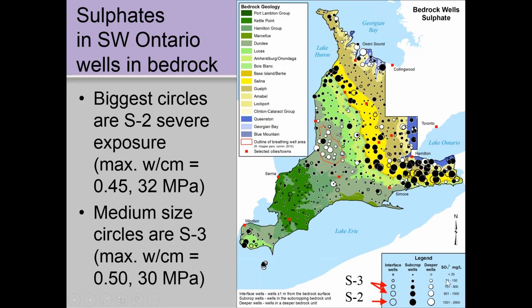Anything less than 150 is considered not a sulfate, so any of the smaller dots are not a problem, but when you get the bigger dots, that's where there are sulfates. And that puts limitations on the concrete, of course. S3, which is the lower moderate category, is 0.5 max water binder ratio and 30 MPa. And S2 is 0.45 and 32 MPa.